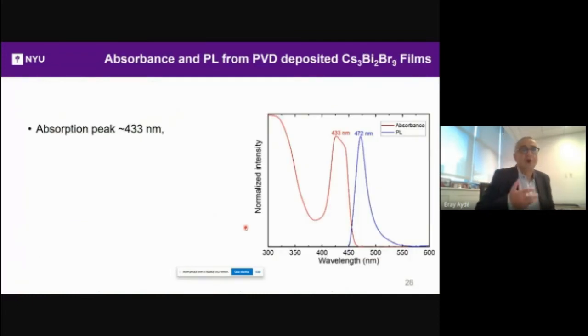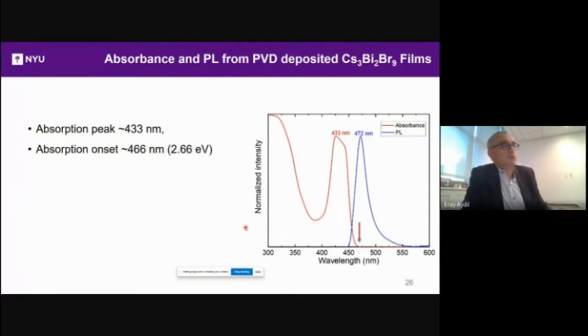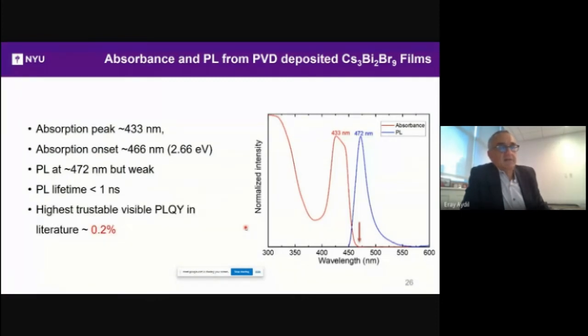So to cap, now the known trustable absorbance and photoluminescence: absorption peaks at 433 nanometers, absorption onset at 466, consistent with a band gap of 2.66 electron volts, and photoluminescence at 472 nanometers, but it's weak. The photoluminescence lifetime is less than 1 nanosecond. So that says there is a lot of very fast non-radiative recombination in that material. In fact, the highest trustable visible photoluminescence quantum yield is not 50%, but less than 1%, about 0.2%. So that's going to become important in a minute.